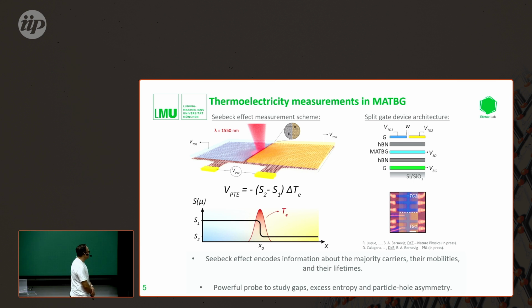So basically, we can, for example, make a device which has a split gate on the top here, which allows us to control the carrier concentration in the different device regions separately, and it allows us to set the Fermi energy in the different device regions independent from one another. And basically, it allows us to induce an imbalance of the Seebeck coefficient, sort of a step function for the Seebeck coefficient across the device.